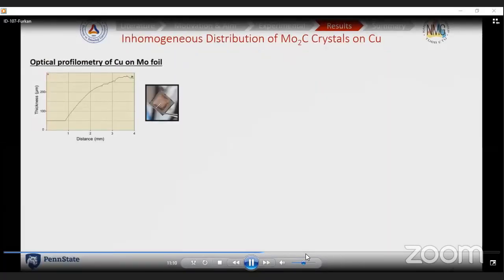So before jumping into the effect of processing parameters on the crystal growth, I want to show you an interesting result, which is the inhomogeneous distribution of molybdenum carbide crystals on the copper substrate, which is caused by the wetting behavior of the liquid copper on the molybdenum substrate. And as you see from the original photograph and also from the optical profilometry of copper, the thickness of the copper on molybdenum is not the same for different regions on the copper substrate. So at the center region it is thicker, but at the edges it's thinner, and this leads to inhomogeneous distribution of crystals in terms of morphology, thickness, and size.